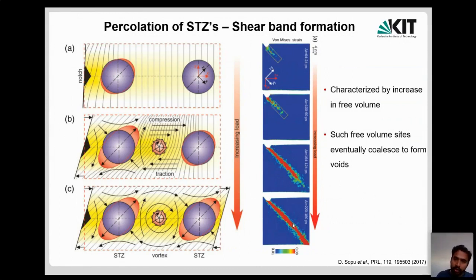And that is why when you pull the material in tension, these bands form very quickly, and the bands have a lot of free volume or a lot of voids in the bands. And if you remember your tensile testing in crystalline materials, you know that at the necking region, the neck forms, and along with the neck you have a lot of void formation. Once the void formation starts, the strain rates at those local regions are extremely high and the material breaks.